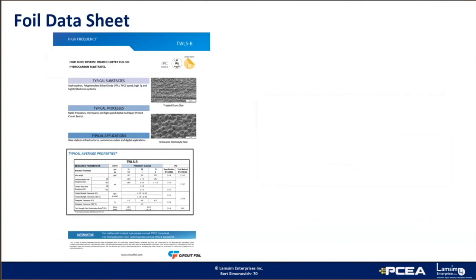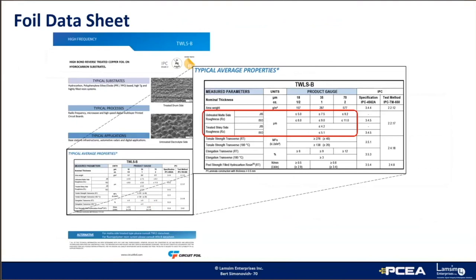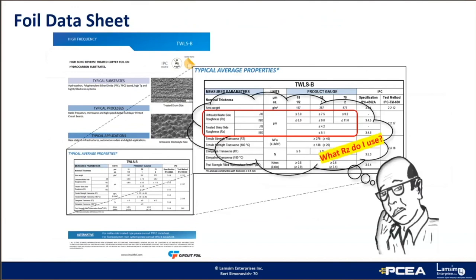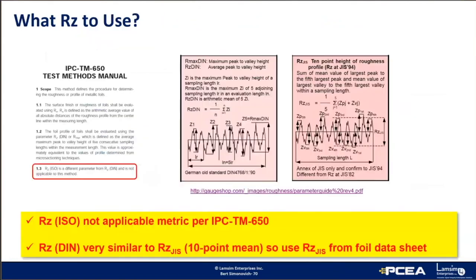Here's another example of a typical foil data sheet. But as you can see, there are two RZ numbers for the mat and the drum side, JIS and ISO. So the question is, which RZ do I use? When we look up RZ ISO in the TM650 test methods manual, RZ ISO is not recognized as a roughness parameter. Asian foil suppliers tend to use the JIS method, which is the same as the 10-point mean method.